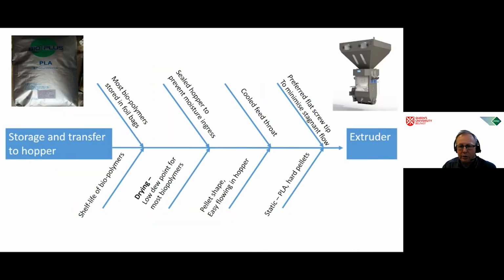So firstly, if we look at how we store and transfer biomaterials, most biomaterials are hygroscopic, so they will very readily absorb moisture, and any moisture present, if that's then put in the extruder, will severely degrade the polymer. It will break down the polymer chains, and you will have no control, and you'll not be able to make an acceptable product. So these resins are typically supplied in foil bags for this reason, but it's also usually recommended to dry these materials to moisture levels of something like 0.04% or even lower. For this reason, inline drying would also eliminate any moisture uptake.